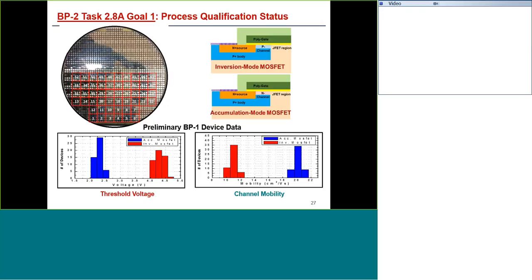This is still a normally off device, or an enhancement mode device, with a positive threshold. The difference is that the N- base is used so that we have an accumulation layer for the channel, and we have shown in the past that that will give us better mobility. So that is confirmed in the devices that were made in BP1.